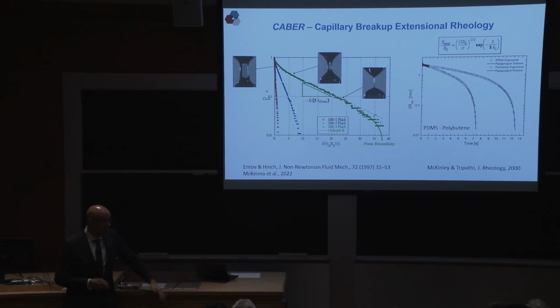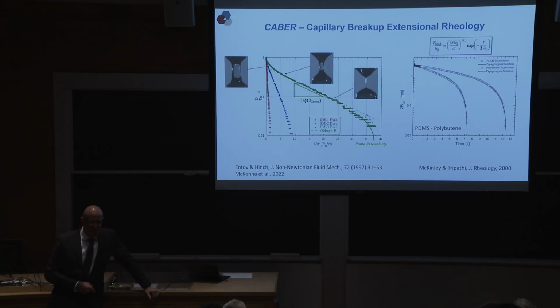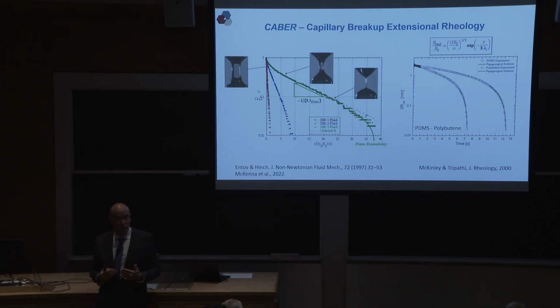So one idea, and again, this is a plug to my friend Professor McKinley here, is to think of different ways of measuring rheology in a high throughput manner. In this example, they have something that they call CaBER, capillary breakup extensional rheology, where they take a polymer sample, a little drop, and they separate it. It forms a filament. The filament thins as a function of time as you separate the two surfaces that hold the drop until it breaks. And from the variation of the diameter of this filament as a function of time, they can back out the rheology. Of course, if you have a good model to describe this rheology, you can extract many more properties than if you have a bad model. So can we use these slip spring methods to do that? And of course, if this works, you can have many, many droplets and just take video of all of the different materials and extract rheology.